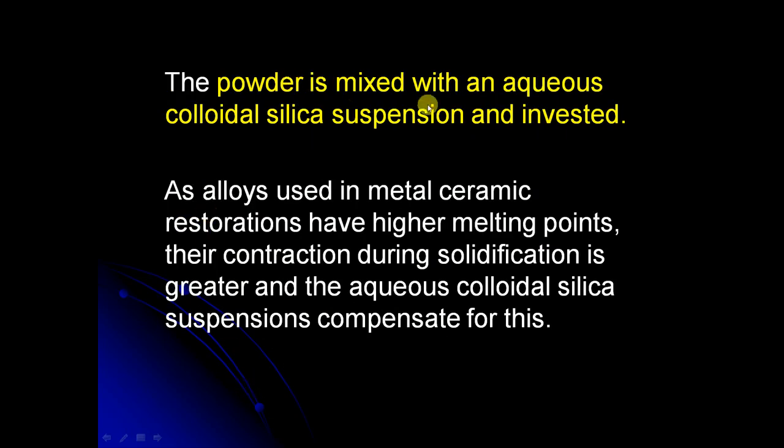The powder is mixed with an aqueous colloidal silica. In this we are using aqueous colloidal silica instead of water, and invested. As alloys used in metal ceramic restorations have higher melting points, their contraction during solidification is greater, and the aqueous colloidal silica suspension compensates for this.